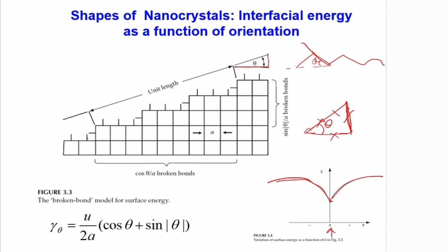First is that crystallographic planes of an FCC crystal have different numbers of broken bonds per unit area, so they have different surface energies, different values of gamma. Here, gamma is the specific surface energy per unit area, right? We are talking about that. Please remember this. I should not come again and again to the same concept. And this is now connected with a generalized concept. Why should you talk about only FCC? It can be true for any crystalline structure.